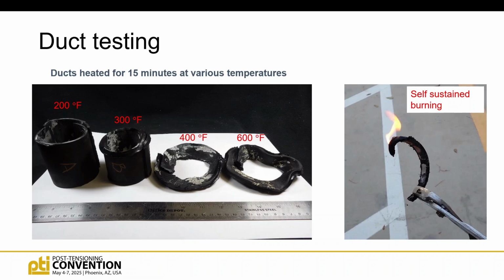We did find out that they ignite, and they burn very slowly all by themselves. And so that's what caused the ducts to just melt off. And that also caused a lot of our soot. So the ducts burned off. They burned off very slowly, and it's fire, but it's low heat, right? It's not a raging inferno. But they cooked off very slowly over time, we think. And so that was not usable as far as determining how the tendons were affected by the heat, just because the ducts themselves were on fire.